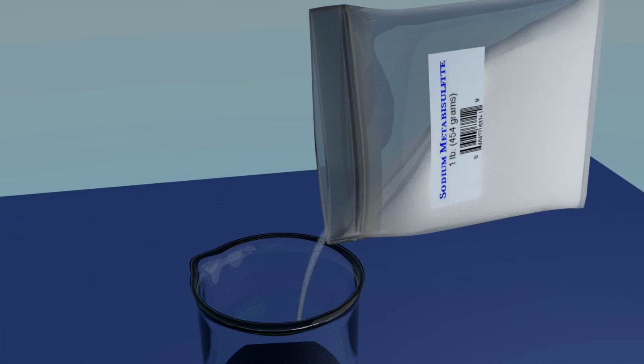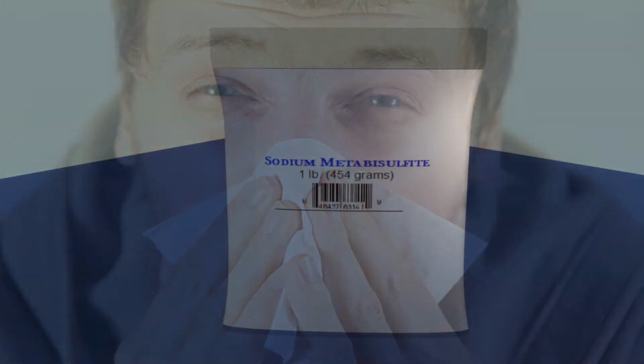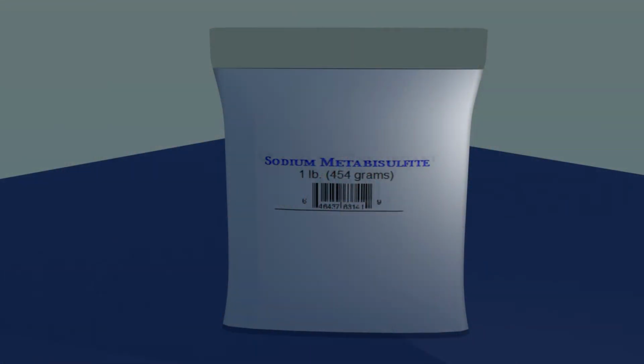For smaller-scale refining, the traditional choice of precipitant is sodium metabisulfite. While not as corrosive or toxic as sulfur dioxide gas, it produces, when added to solution, sulfuric acid and sulfur dioxide gas. If using this precipitant, you should precipitate your gold, out of doors, with a good breeze at your back. Otherwise, you will find yourself coughing, and your eyes, tearing. Since there are good, non-toxic alternatives to sodium metabisulfite, notably, oxalic acid and ferrous sulfate, there really is no good reason to use sodium metabisulfite.